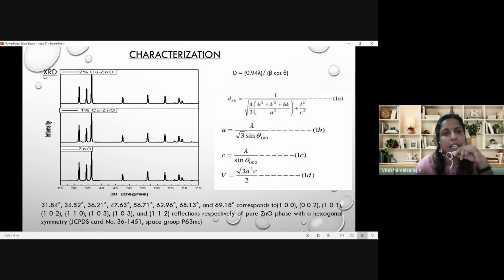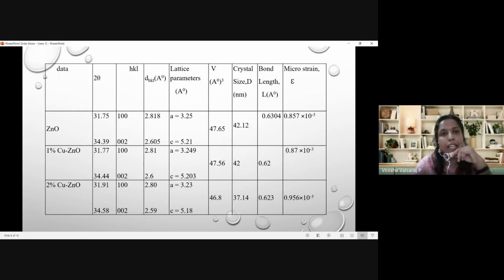First of all, the XRD analysis showed that these three materials have a highly crystalline nature, and these are the different 2 theta values corresponding to different planes that confirm the hexagonal wurtzite structure of this material. Using the Debye-Scherrer equation and other equations, we found the different lattice parameters, volume of these materials, bond length, microstrain, etc. From this data, we can clearly see that ZnO and the copper-doped ZnO have the same lattice parameters. So it confirms the wurtzite structure of ZnO after doping also.